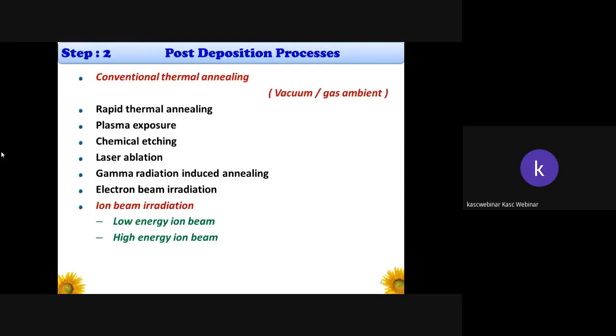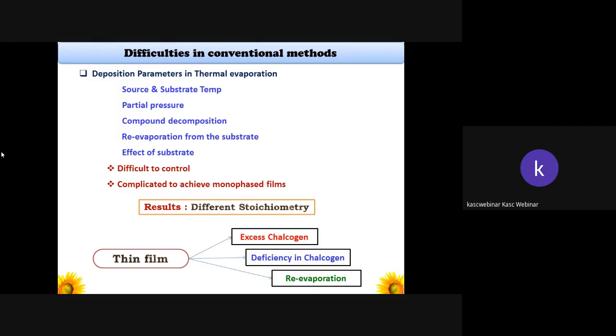And as I said earlier in step 2, the post-deposition process, while I have chosen this conventional thermal annealing method to tune the property of a material, what are the difficulties one can face? The first thing, by using thermal evaporation techniques, if I have prepared a material, the deposition parameters in a thermal evaporation technique, called source to substrate temperature and the partial pressure involved in the preparation technique, and compound decomposition and re-evaporation from the substrate, and also the effect of substrate. These parameters play a crucial role in deciding the material properties.